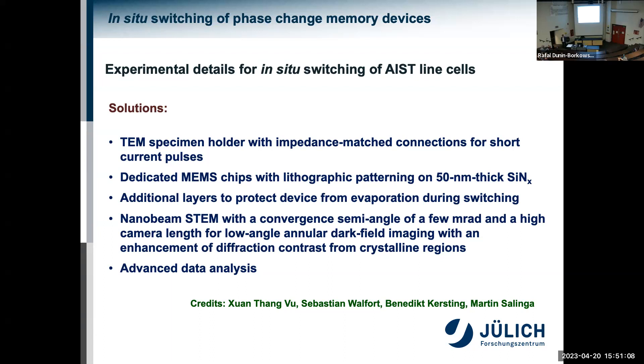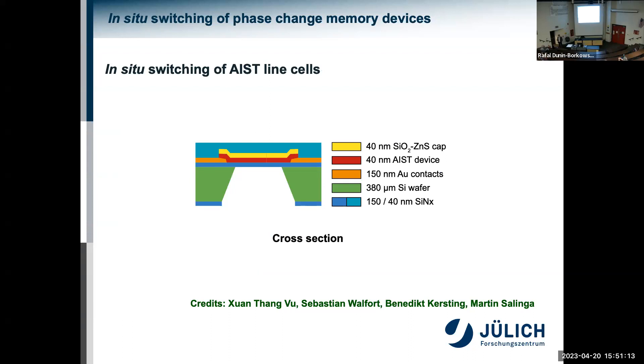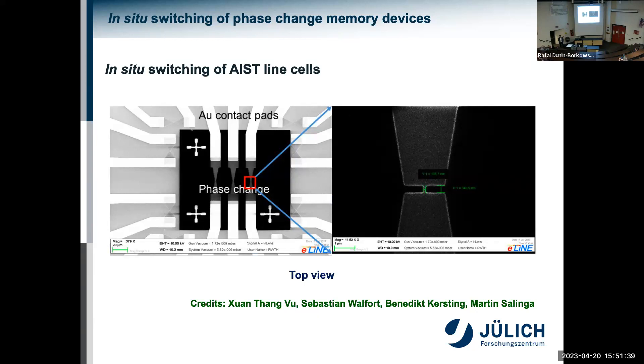The entire stack has an electron-transparent region in the middle. The red layer — labeled AIST, silver indium antimony tellurium — is the active switching device, with additional protective layers of silicon nitride above and below. In a scanning electron microscope at low magnification, you see gold contact pads and gray regions of phase change material getting narrower. The device itself is just 40 nanometers tall and about 50 nanometers wide — the small constriction at the very center of the image that we want to examine during switching in the electron microscope.